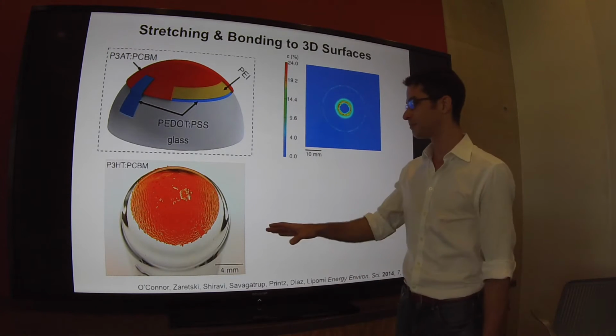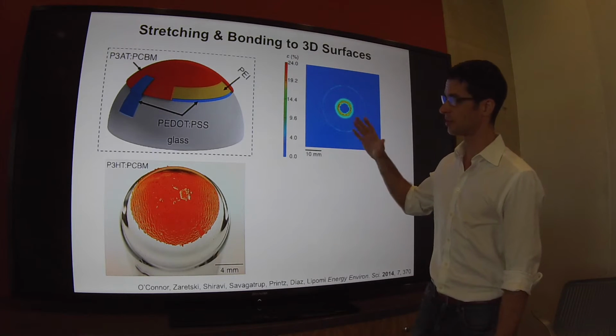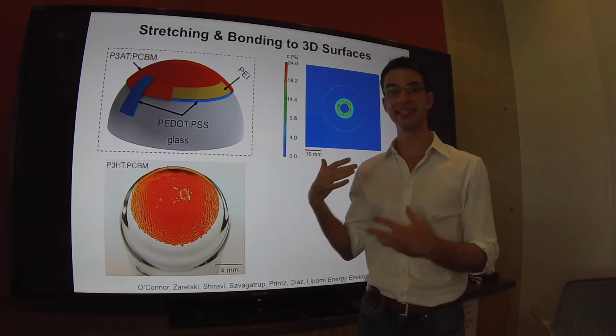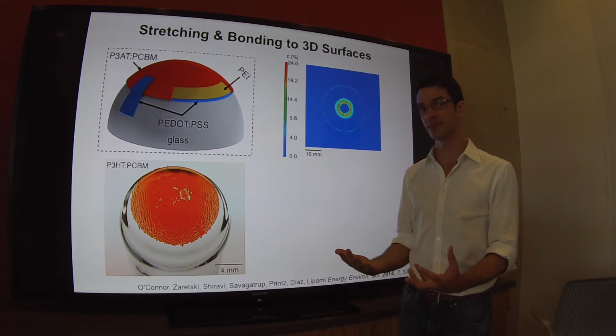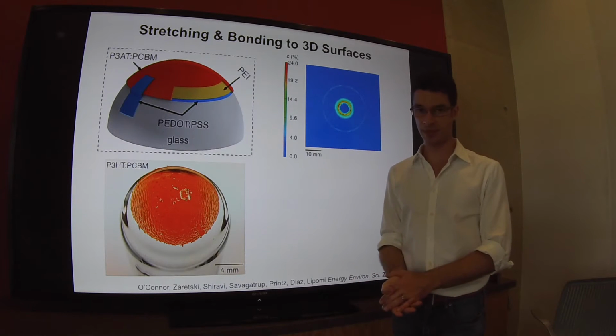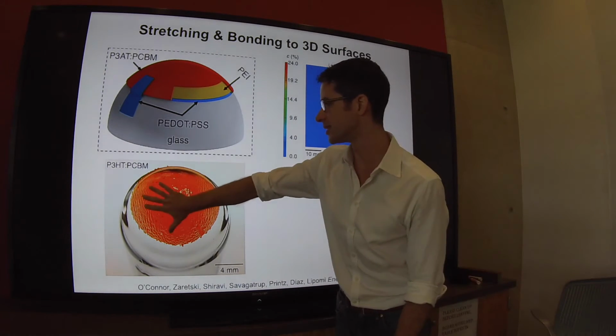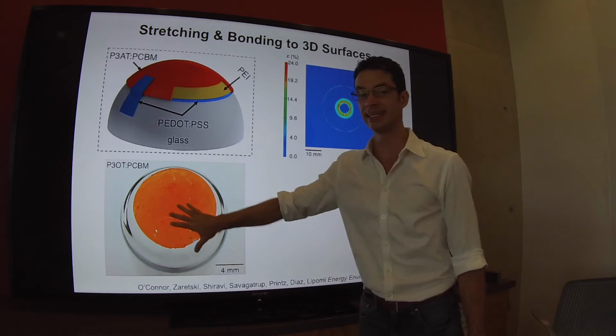Our analysis in the previous slide said that the C6 polythiophene would not survive this transfer, but that the C8 polythiophene would. And that's what we see here. The C6 polythiophene is cracked, and the C8 polythiophene gives you an intact device.